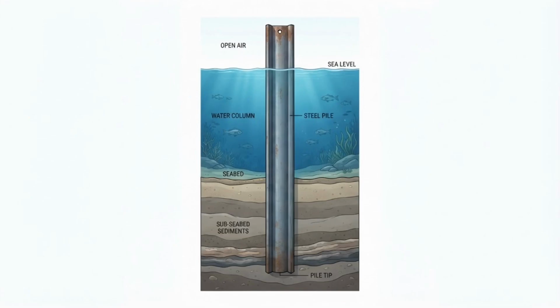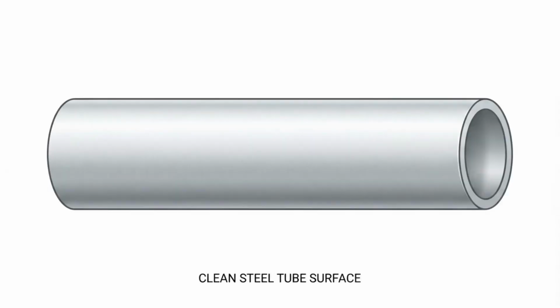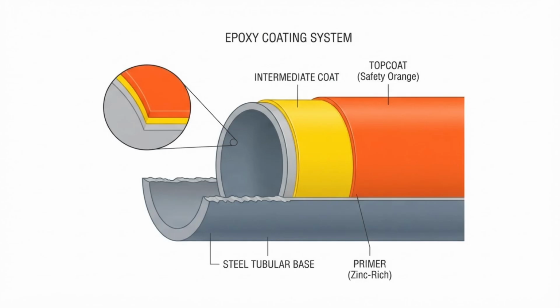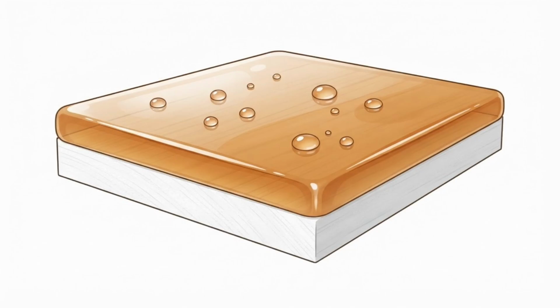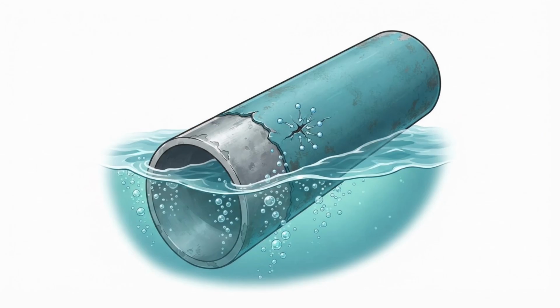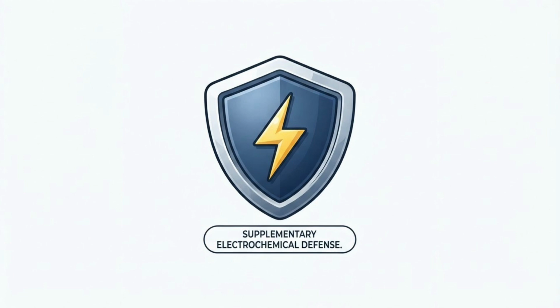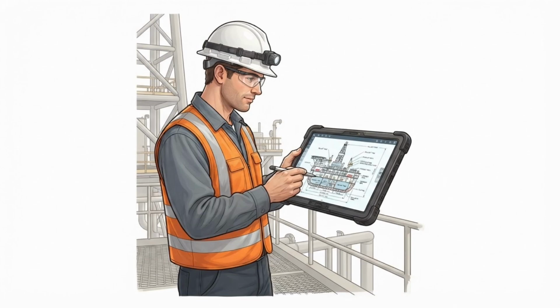Because this steel will spend its entire operational life submerged in highly corrosive seawater, it must be fiercely protected. The entire structure is blasted with high-pressure abrasive grit to strip away any mill scale and expose the raw, white metal underneath. It is then rapidly coated in multiple layers of heavy-duty marine epoxy and polyurethane paint, creating a thick barrier against the salt water. However, paint alone is never enough.